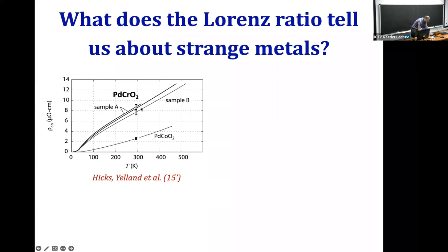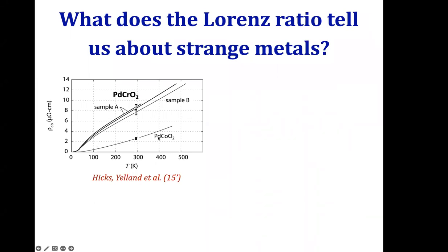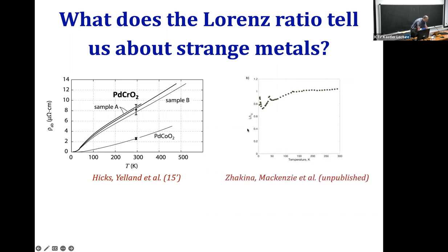From comparing that to a sister compound, palladium cobaltate, they argued that this linear in T may not be due to phonons. That's the usual mechanism to get linear in T resistivity at high temperature. The reason is that palladium cobaltate has an identical structure and a very similar phonon spectrum. The only difference between these two materials is that the chromate has localized magnetic moments on the chromium ions and the cobaltate doesn't. You see this big difference in the resistivity, and also the resistivity in the cobaltate is not quite linear. But it turns out that if you look at the Lorenz ratio in the chromate material, in the region where the resistivity is linear, that approaches one within a few percent. So this is a very strong hint that the source of this linear in T resistivity is coming from elastic scattering processes from some slow degree of freedom, presumably not the phonons, nevertheless. And of course, there are some puzzles.